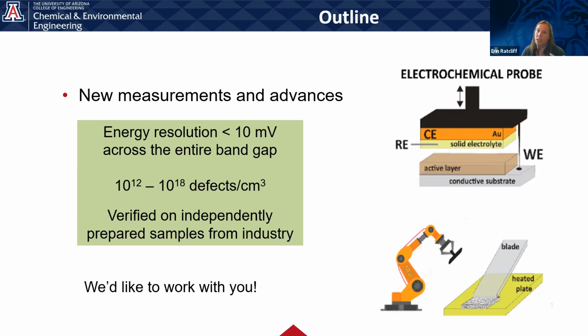Limit of detection in our differential pulse voltammogram approach changes, and it's a little bit material specific because we have to balance that capacitive current versus that Faradaic current. This has been verified. Everything that I've shown you so far is samples that are prepared in our group, but we have verified our approach on industry relevant prepared samples, and that our defects that we're measuring in our device are equivalent to what we're measuring for our industry partner.